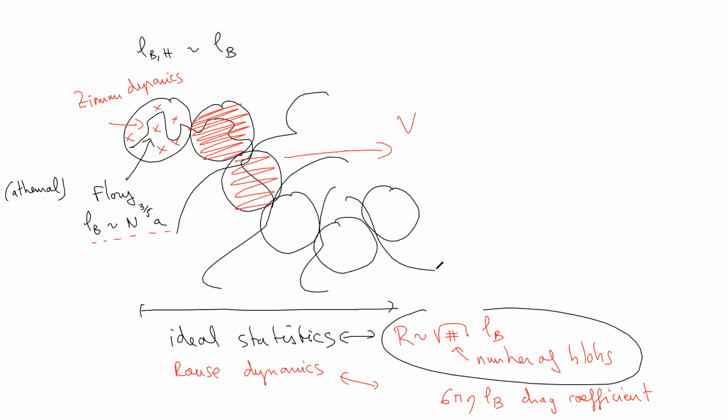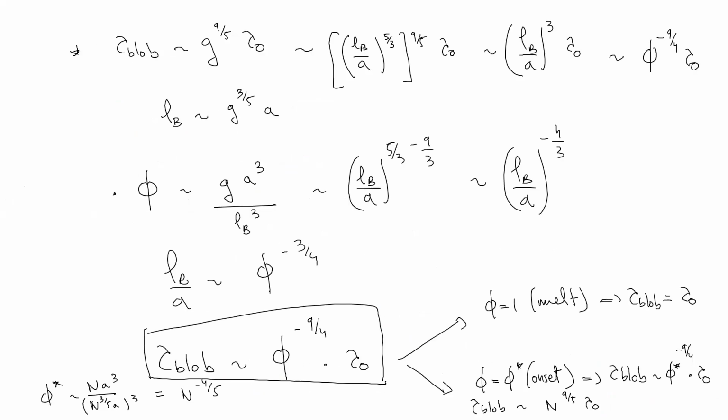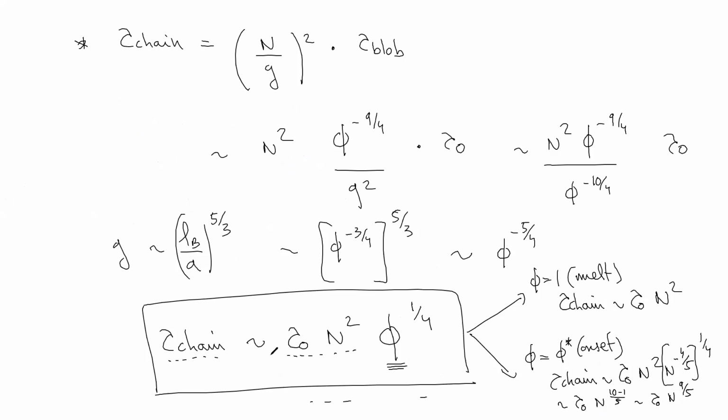It's a melt of blob-like chains. We know what's going on inside the blob. There is no other chain here, and there are interactions, both static and hydrodynamic, with the solvent. And outside the blob, you screen those interactions out, and you are left with an ideal picture of a blob chain and a Rouse dynamics. And so you can, at every length scale, describe the relaxation time, and thus end up with the total relaxation time of your problem.